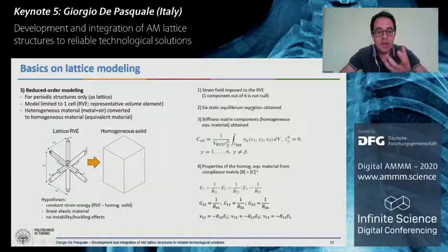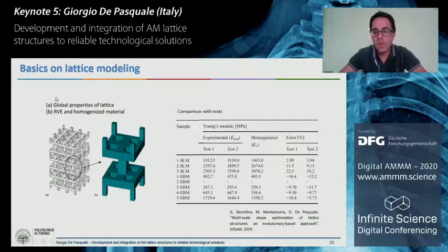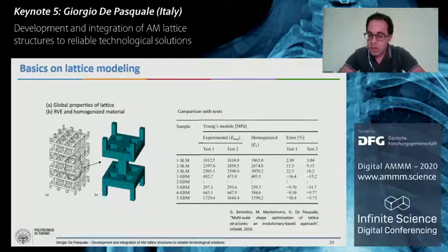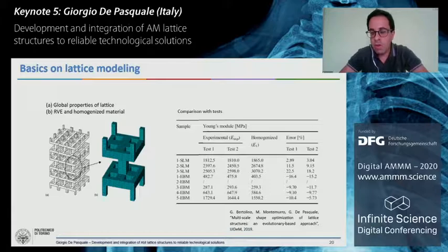And we use this brick, let's say, very easy and simple shape to make our models in a much faster way with very low computational heaviness. For example, in the case we saw before, for the cubic cells, we can study only one representative volume element and study its behavior and then extend the properties all over the volume. In the results in this table on the far right, we can see that the errors are pretty low. And these errors also include the border effects of the samples, which are quite small, so these effects are not very important.